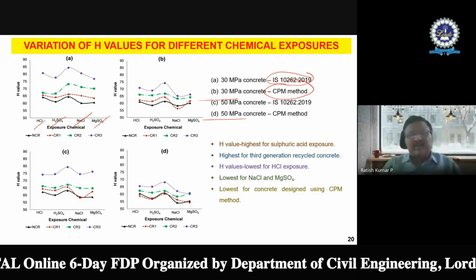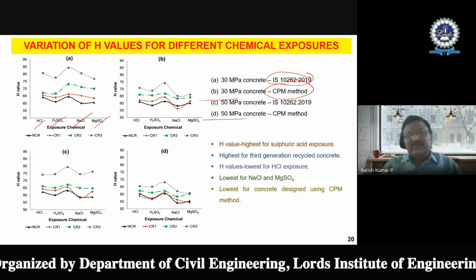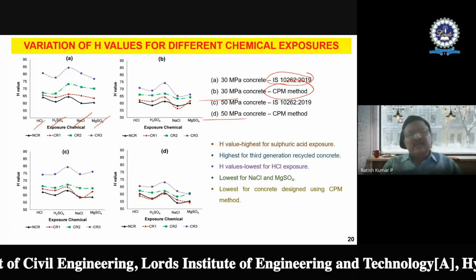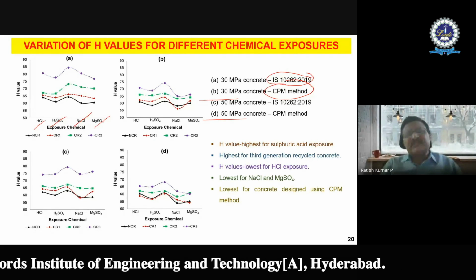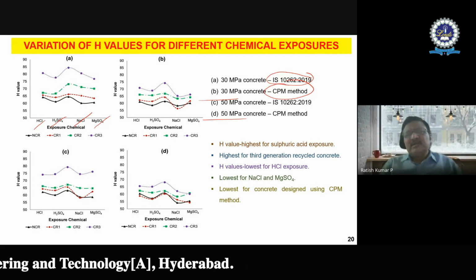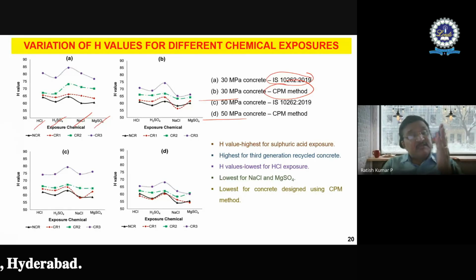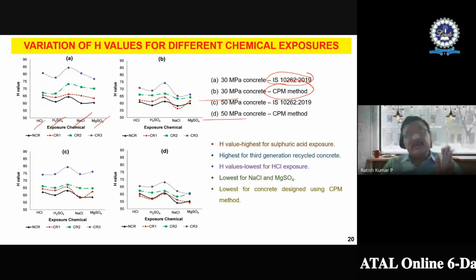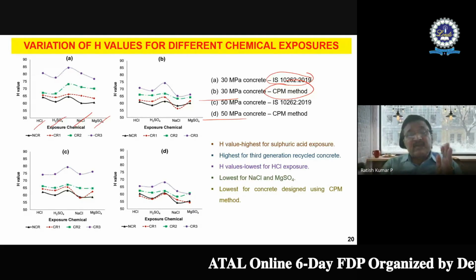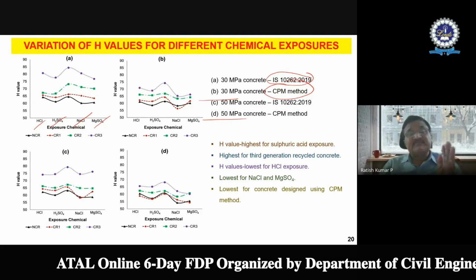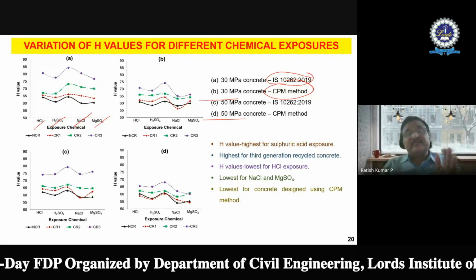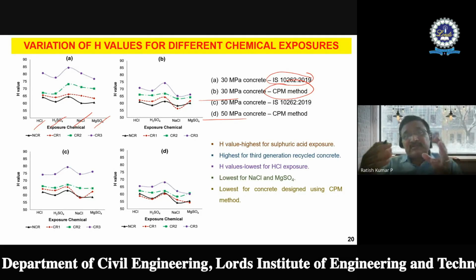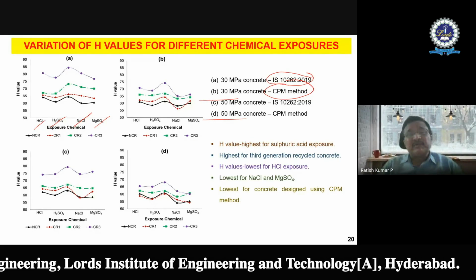The chloride attack as well as carbonation, for example, are very serious as far as corrosion is concerned. And as you know, more than 40% of structures get damaged because of chloride attack. And chloride attack can be intrinsic, it can be extrinsic also. Please remember, it is intrinsic when you make a concrete which already has a good amount of chloride content, more than the acceptable value. It could be extrinsic, where your structure is in the proximity of a chloride environment.